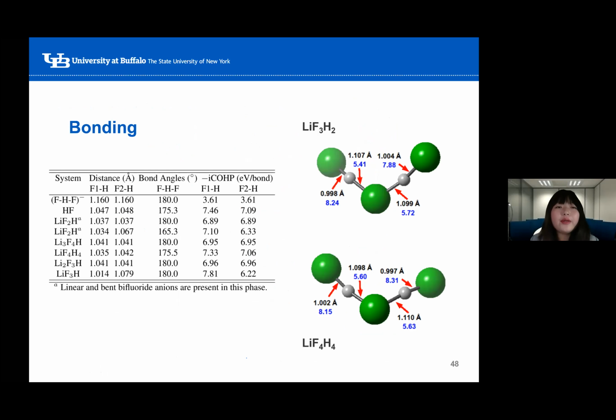So we also carried out integrated crystal orbital Hamiltonian population analysis on the bifluoride and trifluoride anions. These values represent the bond strengths. So in the table, we only analyze the bifluoride anions with the 3 atoms. Comparing to the gas phase model of the linear symmetric anion, the anions in the ternary phases under pressure would have shorter bonds and be stronger.